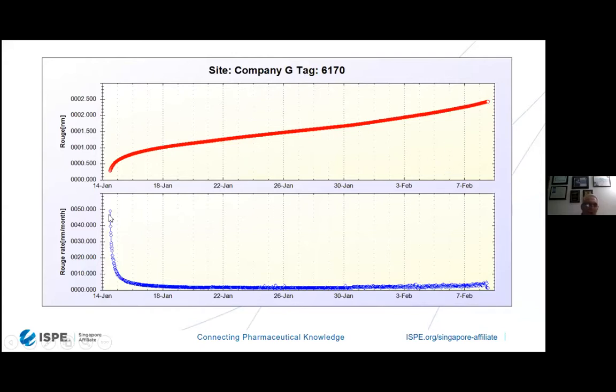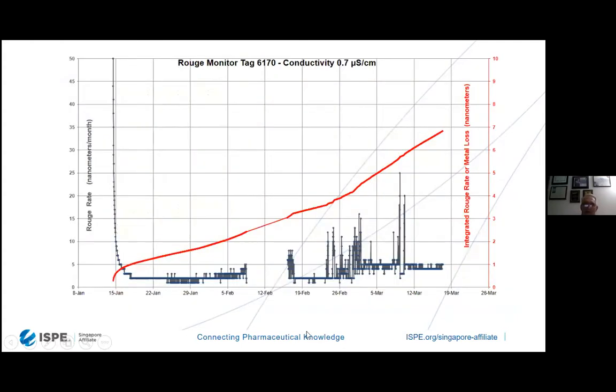The blue line at the bottom, though, is actually the reading every 20 minutes, which shows how the rouge monitor reacts to the water chemistry inside and the temperature and the operations of the water system. Also showing on January the 14th installation, it takes about 24 hours for the probe to acclimate itself inside the water system. And then you can see the accumulation starts from there, very, very small, showing indications around 1 or 2 nanometers.